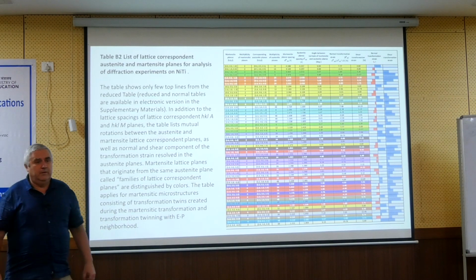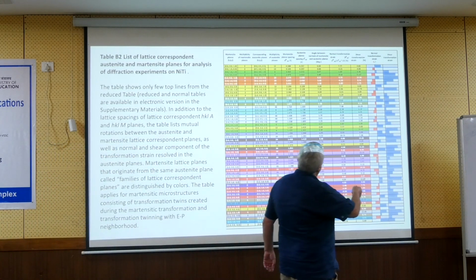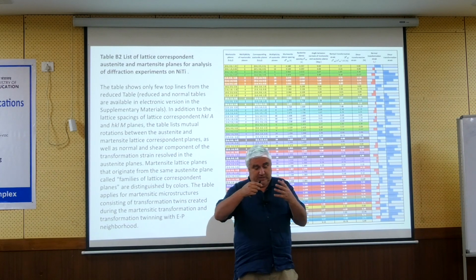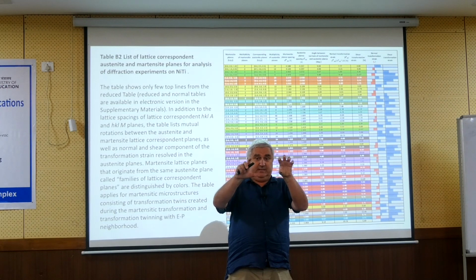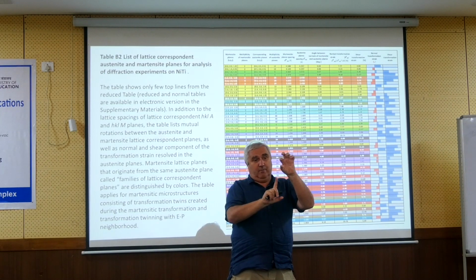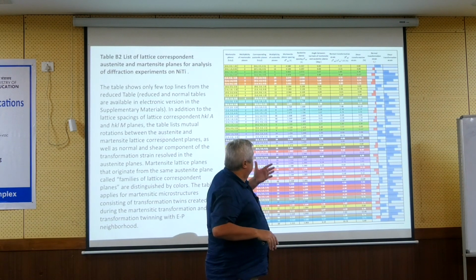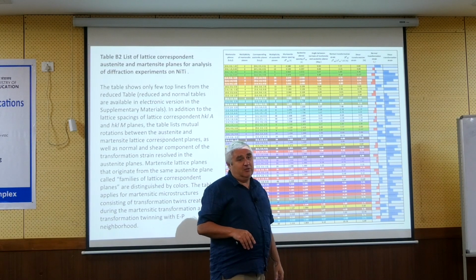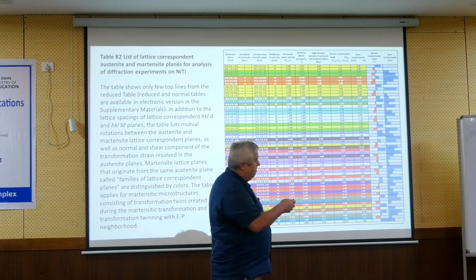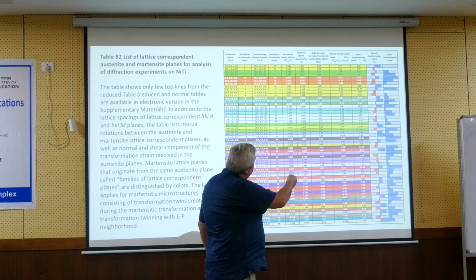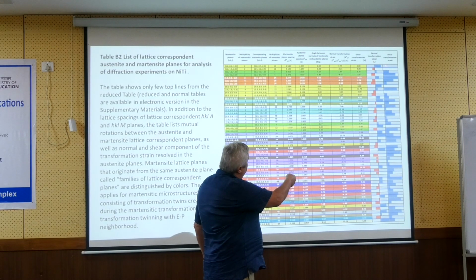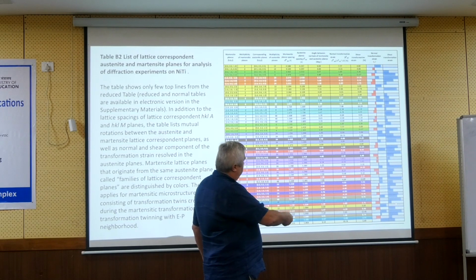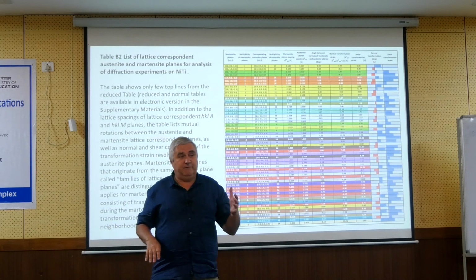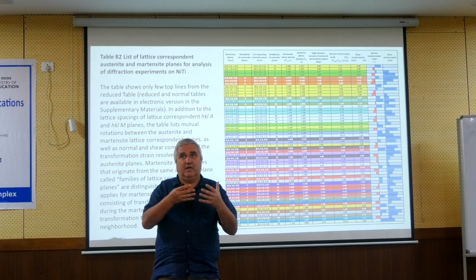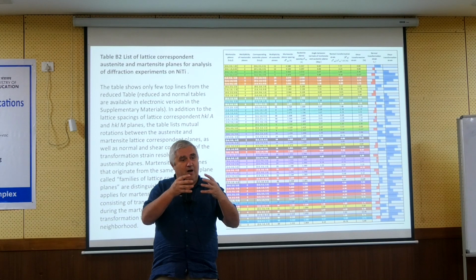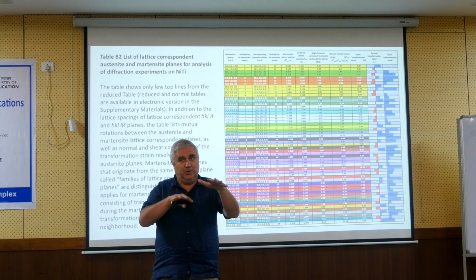What is the explanation for the normal transformation? Well, strain is a tensor, so we can calculate, if this is the lattice spacing, this is the austenite, this is the martensite, the strain in the normal direction, but also shear. So we calculated also shear, and we added it here. I don't really know what kind of meaning it has. We cannot measure it. So this is the tensile strain, compression strain, and shear strain. For example, here there is no shear strain, but here there are some shears added. This would be important if you want to simulate how the atom positions change during the transformation. So you need to know these shears.